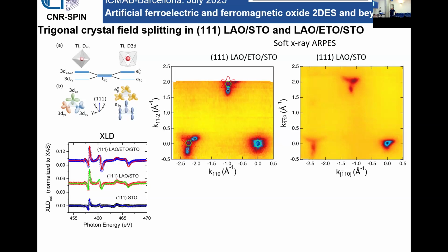So for sure, these models depend a lot on the trigonal crystal field splitting, because Yushen did the calculation. When you start to put in other bands, it's a mess. So if it's a mess, probably all the effects will be enhanced, because every time you have an anti-crossing between two bands, typically the spin-orbit coupling is no longer Rashba-like, it is cubic, and then it is enhanced. We know from 001 LaAlO3 that Rashba spin-orbit coupling is enhanced when you cross the Lifshitz point. And probably I think this comes more from these anti-crossing points, these nonlinear effects, which for sure is interesting physics, okay? But the model is not correct, in my opinion.